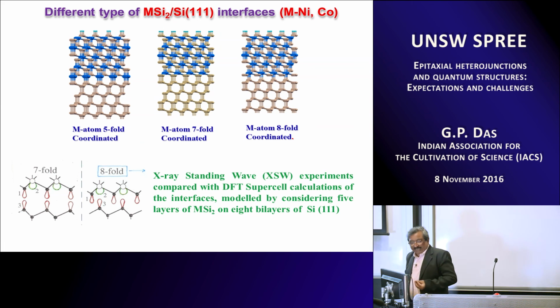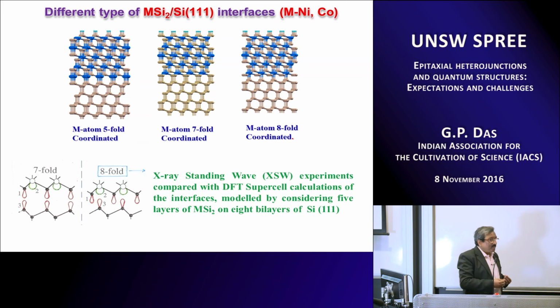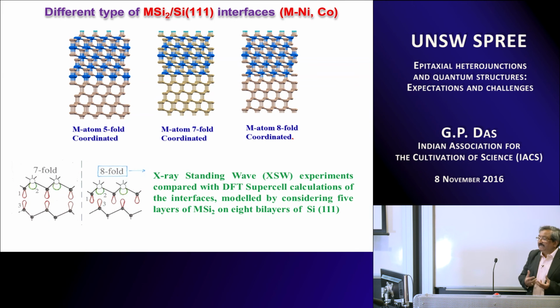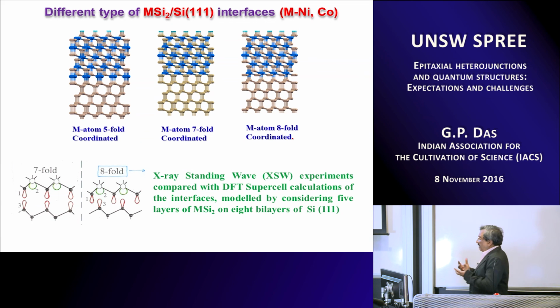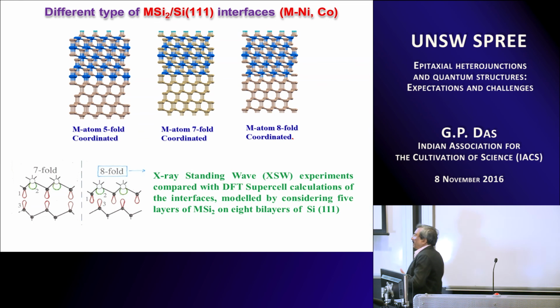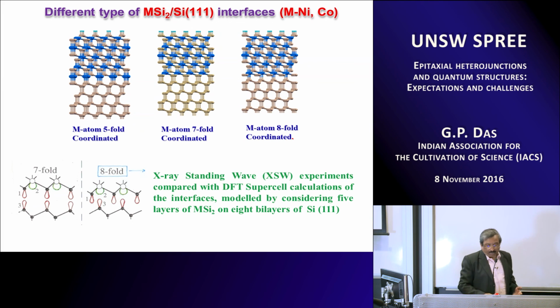See, this is very important and very interesting. How crucial is an electronic quantity like Schottky barrier height on the geometry of the interface, which is epitaxially grown, let's say, using MBE. Now, there have been very accurate X-ray standing wave experiments in Hamburg.